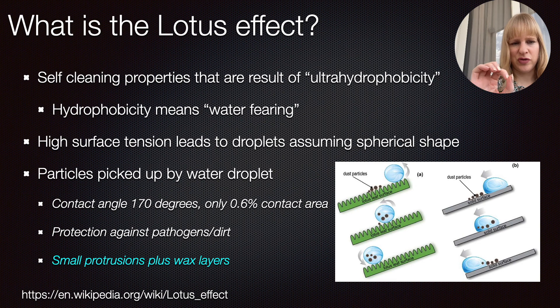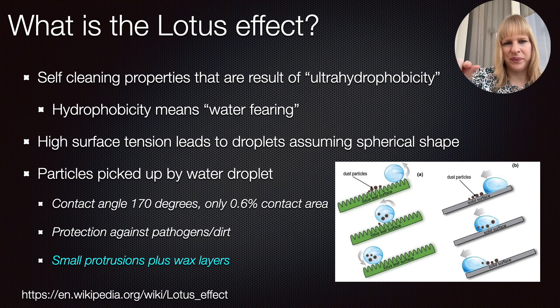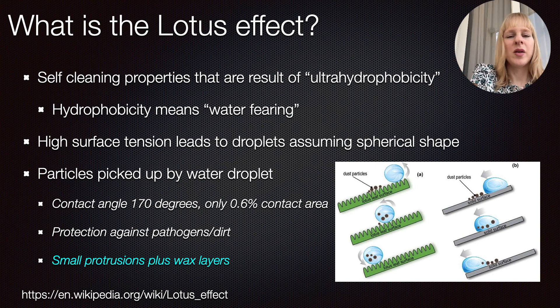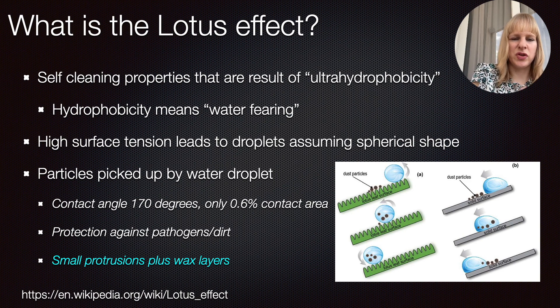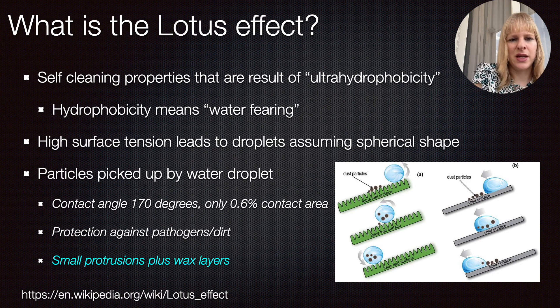It's actually a double structure. Part of it is the macroscopic structure where there are tiny protrusions — little spikes or indents which cause the ultrahydrophobic effect. But there is a second element: a waxy layer coated on top of these protrusions which also contributes to this ultrahydrophobic effect. This regenerates itself, meaning the plant will maintain this property over its lifetime.